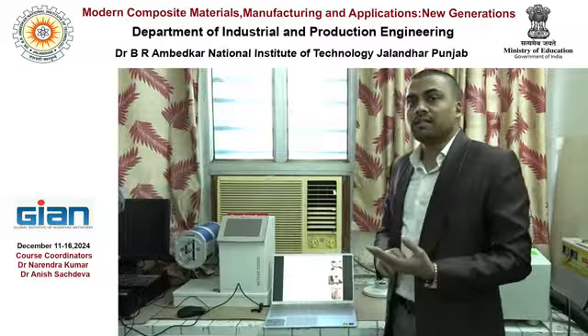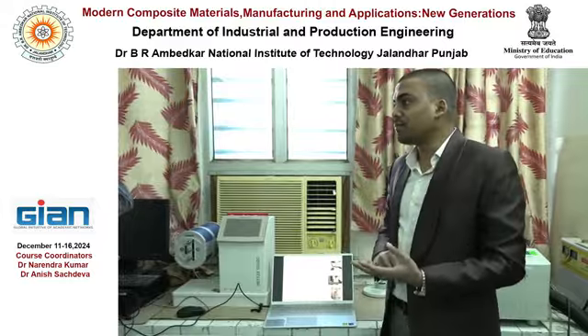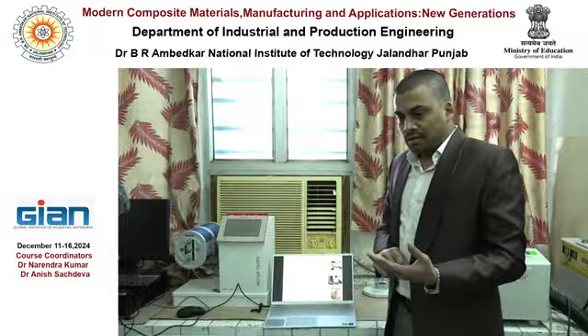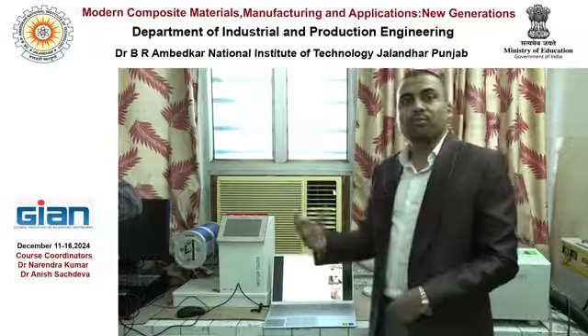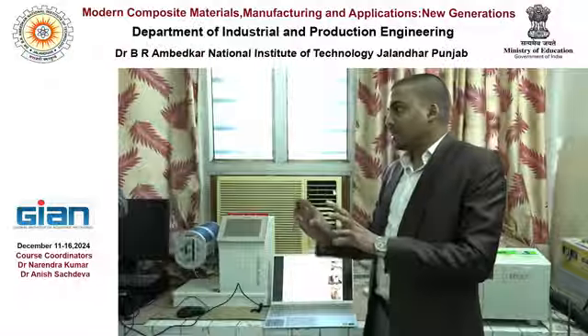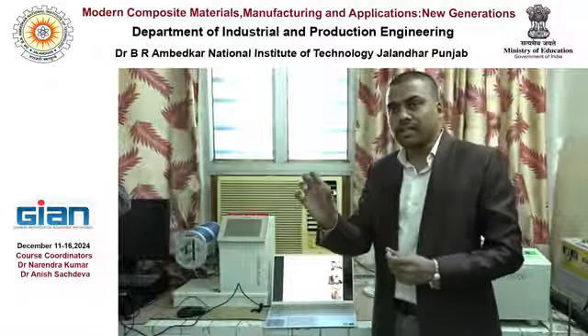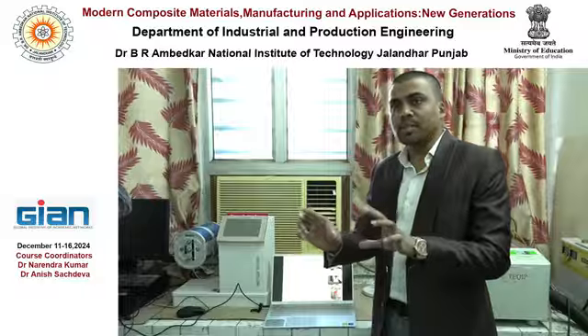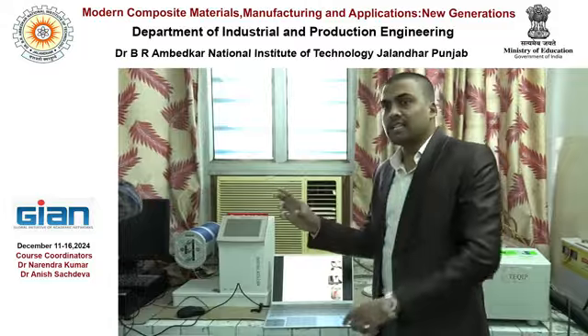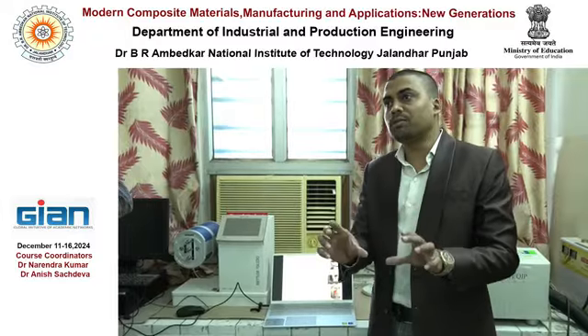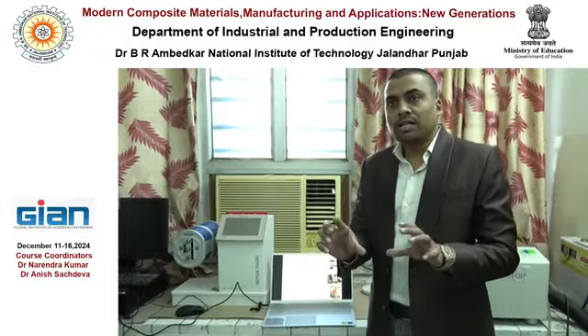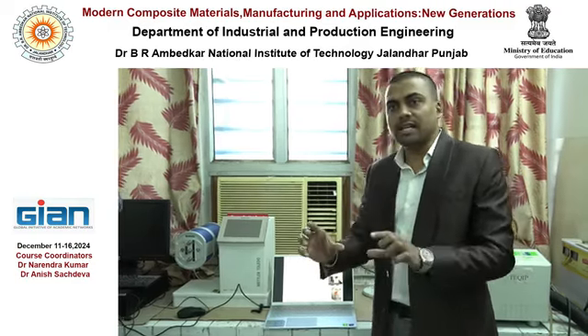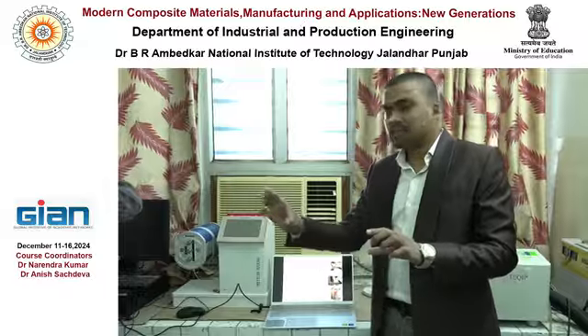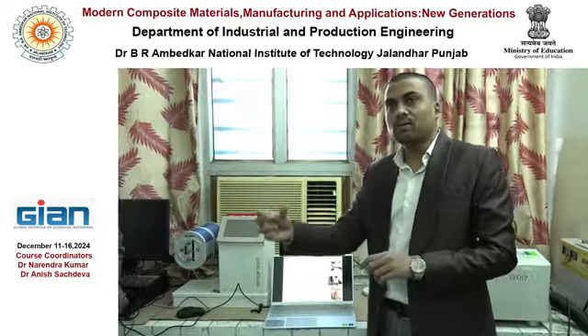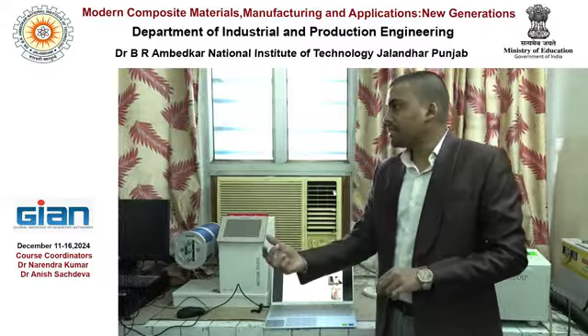It is based on what mechanical performance is required for the particular application. For example, in case of automotive composites, there are guidelines. If you want to use any composite material for the dashboard, there are standard guidelines on how much the tensile modulus of this particular composite should be. It should be around 2.5 GPa tensile modulus. For flexural tests, there is again a guideline for particular components: flexural strength, flexural modulus. Again, for the impact test, there are standards.